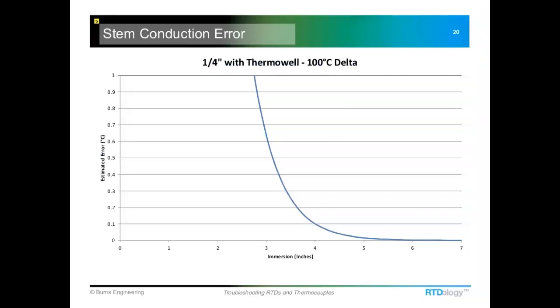So looking at the magnitude of stem conduction, this graph shows an estimate of the error on the y-axis here and the immersion length down here. This would be just a regular tapered stem thermal well with a 1/4 inch diameter probe inside of it. The bore diameter and the probe are matched up; it's typically about a 1/10 of an inch difference between the probe diameter and the bore diameter. This first line here is a 1/10 degree C error, so we're right at 4 inches as a minimum immersion to get a good measurement. The graph here was constructed using water as the fluid. Different fluids will give different results, but this is just to get into the ballpark of what is acceptable.